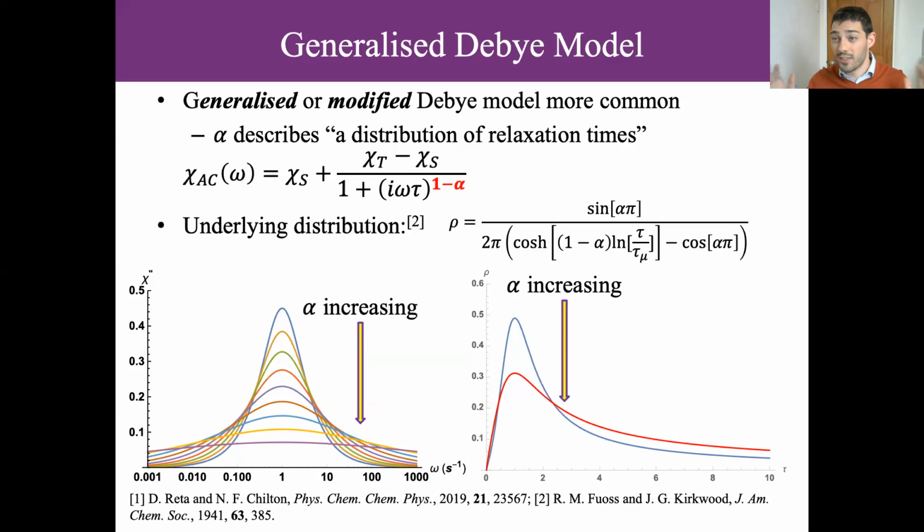So the timescale is very quick compared to the AC fields that we're applying here. AC magnetometry is on the scale of 0.1, 0.01 hertz up to a few kilohertz. There are some people who can do up to megahertz AC, but that's still not 10 to the 12. So the timescales of the electronic spin-phonon processes are much, much faster.